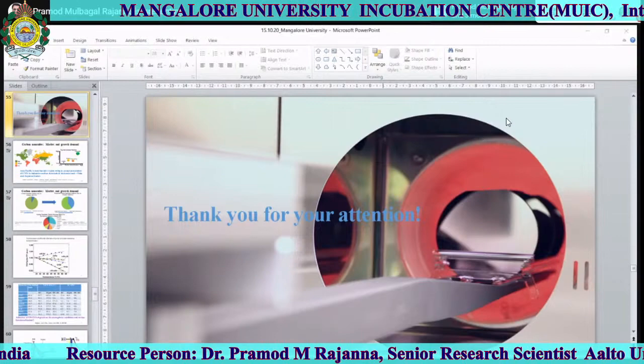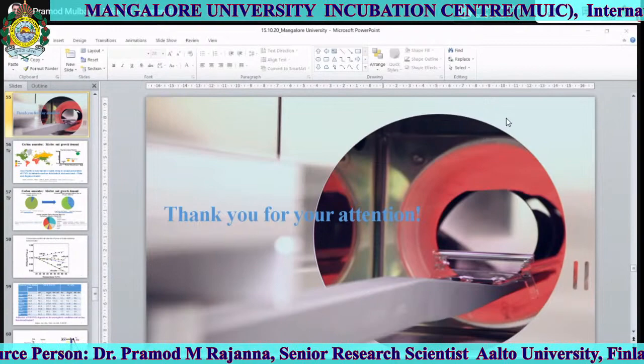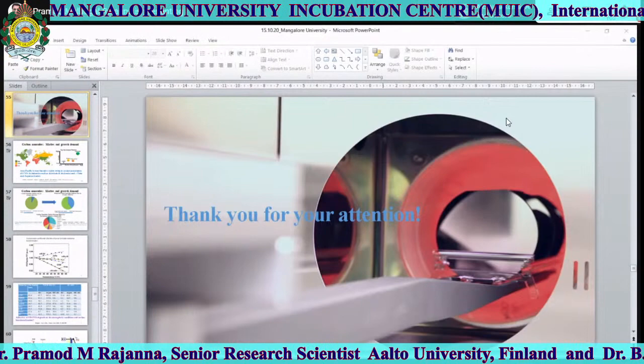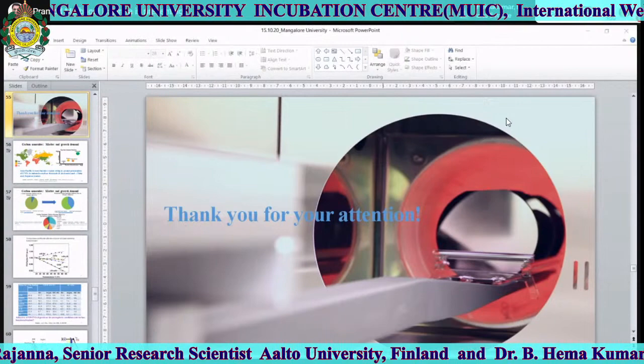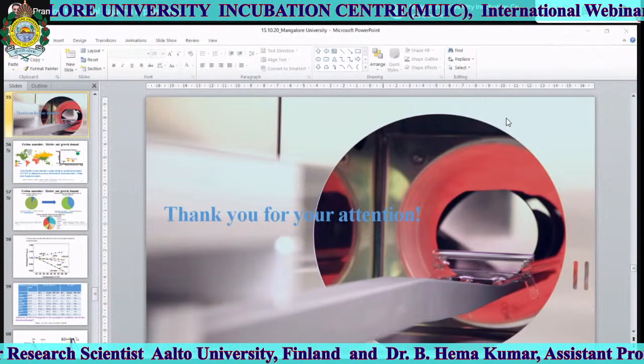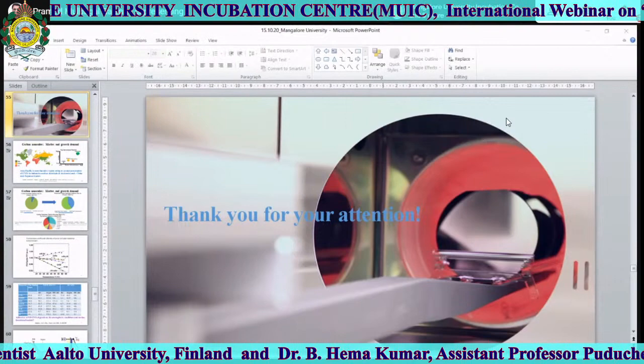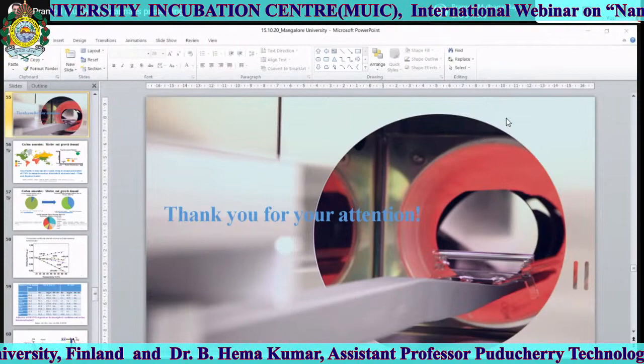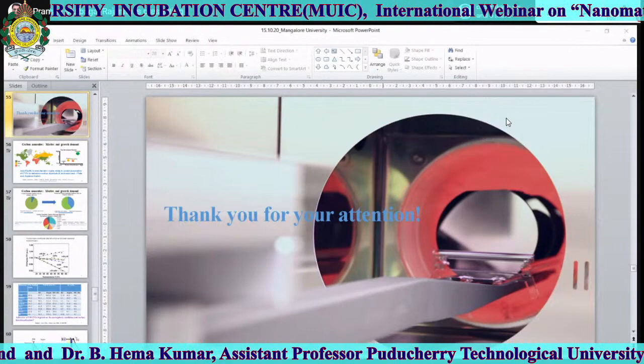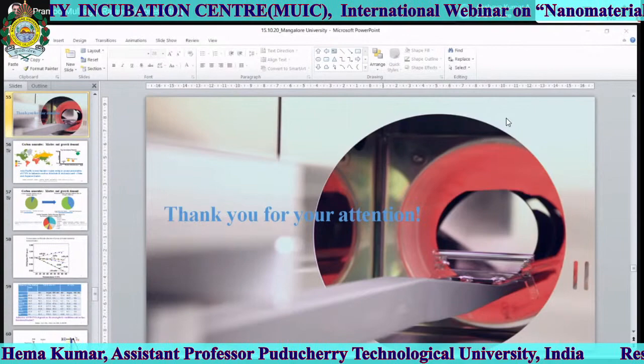That's mainly because of this conductive polymer, PEDOT:PSS, which tends to be not so stable under air and under exposure to sun. That's why, in the challenges and future outlook I mentioned, the encapsulation of the device. The PMMA that we use is also a non-conductive polymer, which could be used for organic devices. But I think it's important to find an alternative, like the way we have done in silicon technology, silicon nitride and silicon dioxide, which are much more stable and industrially compatible. We need to find an encapsulation which is much more stable in air. So these are the two challenges.